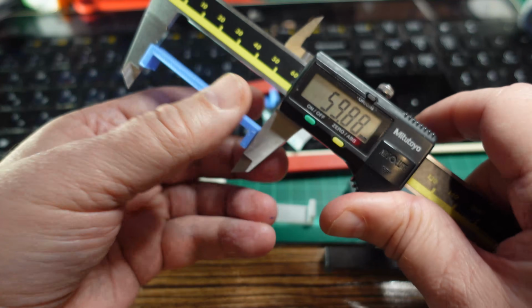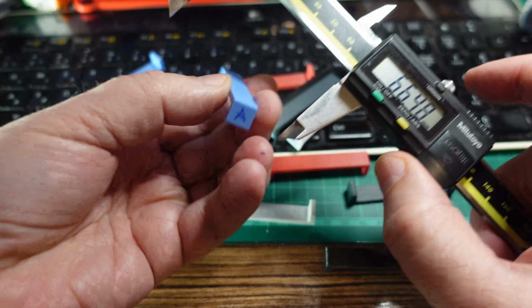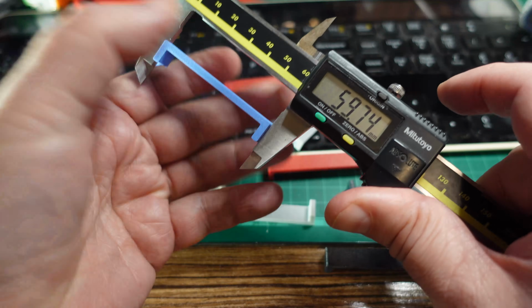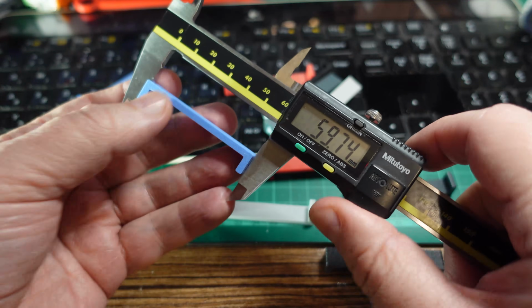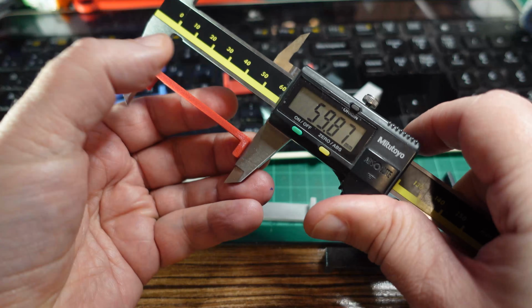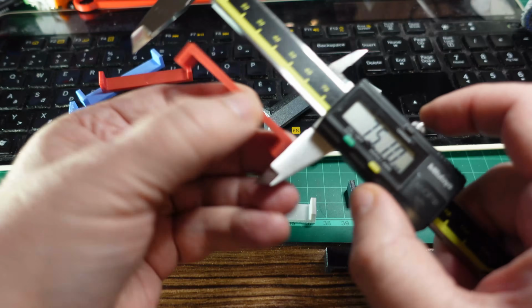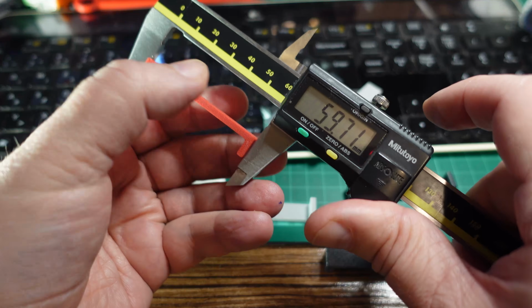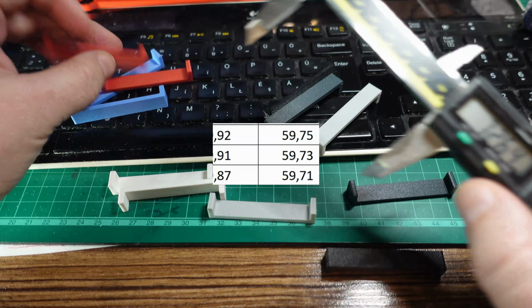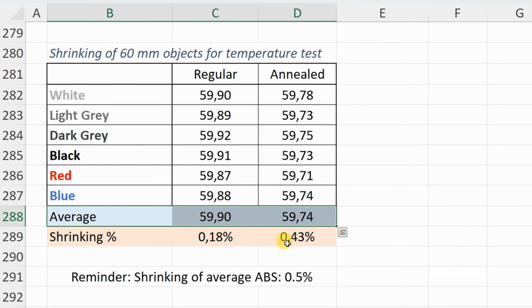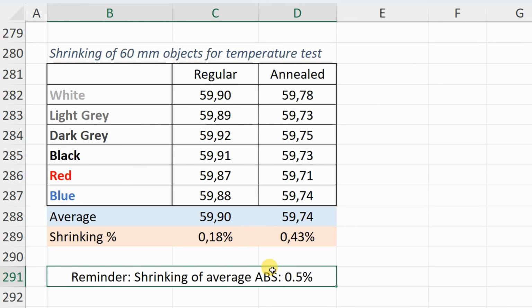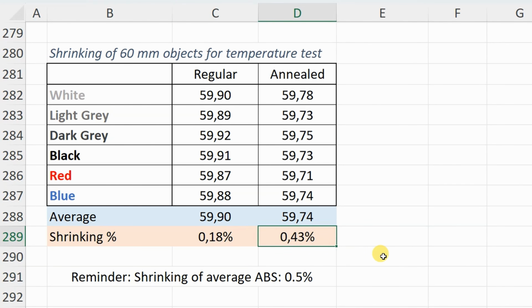Before annealing the shrinking was approximately 0.18%, and after annealing this is 0.43%. Soon I will show you the table. Just in front of the camera I am measuring two test objects. The red color. So in this line you can see the average value, and here is the calculated shrinking. And just a reminder, shrinking of average ABS is approximately 0.5%.